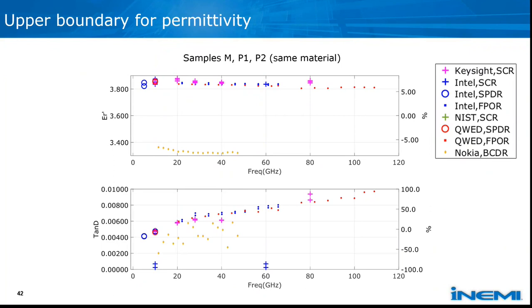So the upper boundary for the permittivity, since we covered the lower boundary for permittivity at the same time as the highest thickness—the highest permittivity material had a permittivity of about 3.8. It's very reproducible in that range. We had no problems with the high permittivity.